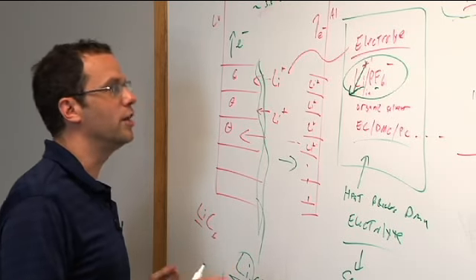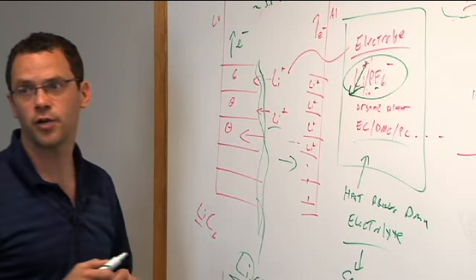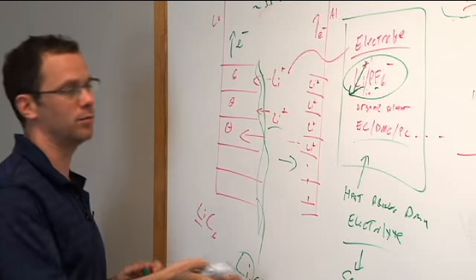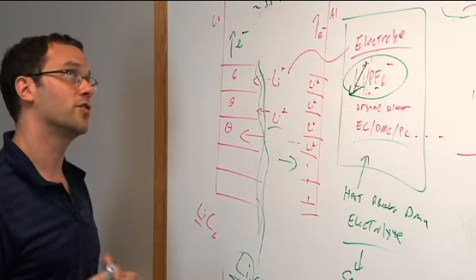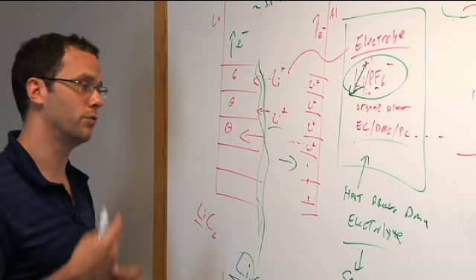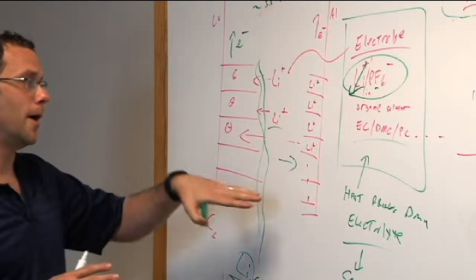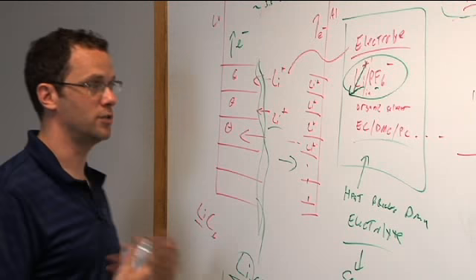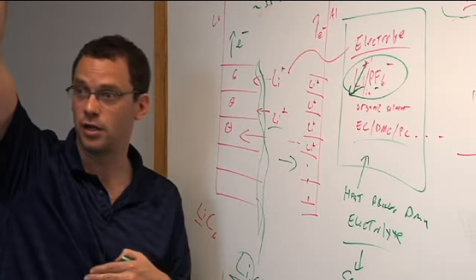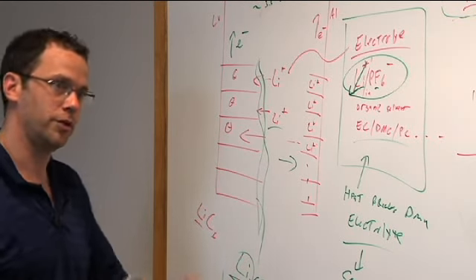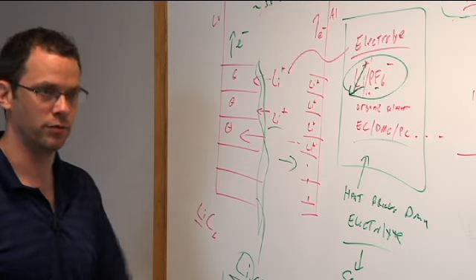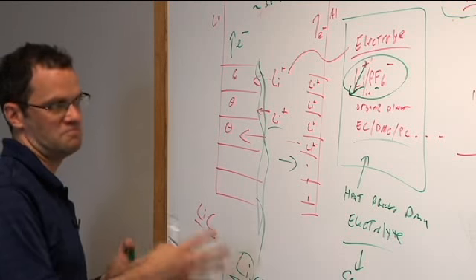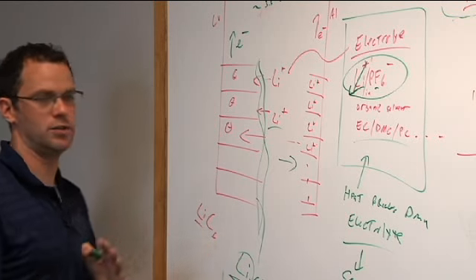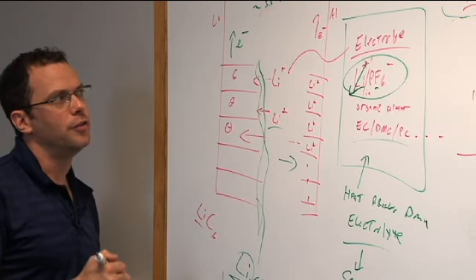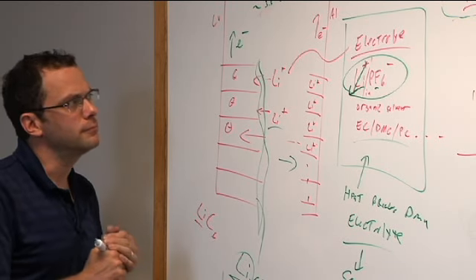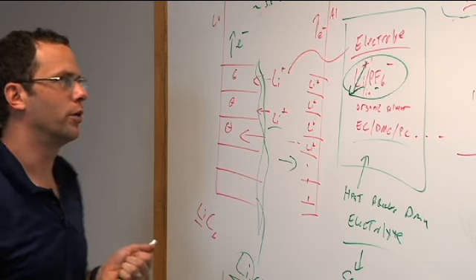That's never good, because you are certainly going to be splitting your electrolyte in that case. The electrolyte is not stable below 0 volts. In fact, electrolyte is not stable below about 0.1 or 0.2 volts versus lithium, so you've got to be pretty careful about going to negative potentials, because it's the same problem as going to over potentials. It's just like a water cell. If you go to minus 1.3 volts or plus 1.3 volts, you will evolve gas. So it's the same basic effects, just on the other side. Most people just don't want to go below a volt, I would say.